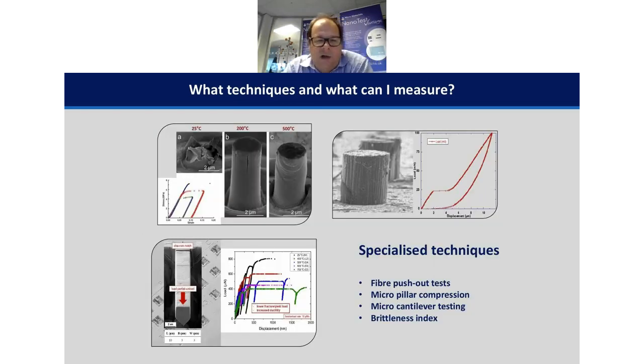There are other techniques as well, and these three tend to be used a little bit more in academia for fundamental characterization of materials. Micropillar compression and micro cantilever bending are used with a variety of different materials, ceramics, metals, etc. In this particular case at the bottom, we're looking at the effects of ion irradiation of tungsten alloys for nuclear power. It's important to use the small scale technique here, because the ion irradiation process only affects a few microns of the sample surface.